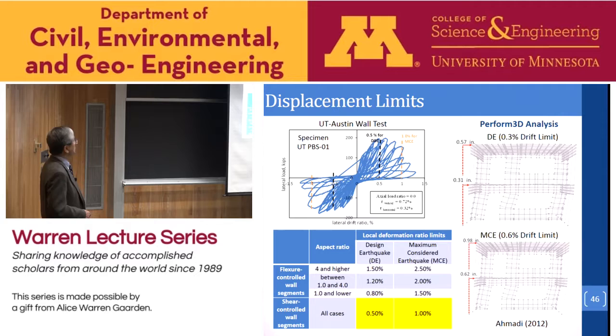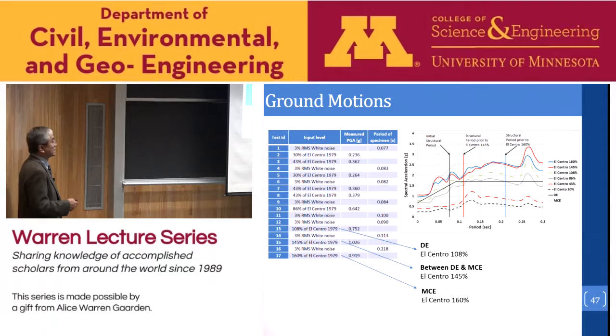And then we did some nonlinear pushover analysis to the drift level and determined what base shear would be required. We also did some time history analysis to make sure the displacement would be within the limit. This structure was subjected to a series of earthquake ground motions, a large number of them. Sometimes in shake table tests, like quasi-static tests, we often overtest the structure because we want to get as much data as possible.